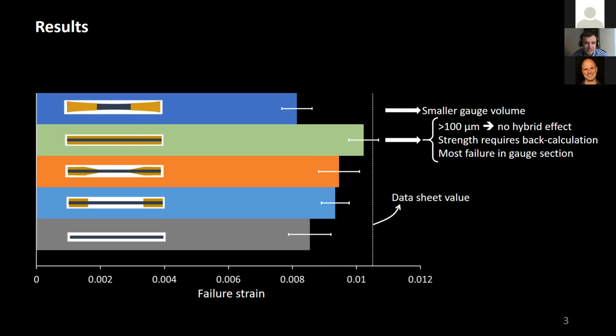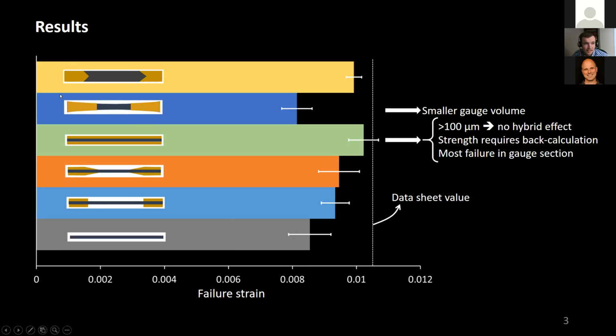the worst test, in the sense that this gave us the lowest failure strain. And I think that is an indication that this was not a very good test, at least not for this specific material. I should also point out that this was the only test that had a smaller gauge volume, which you would actually expect to lead to a slightly larger failure strain or strength. And lastly, we tested the arrow-shaped end taps, and they actually led to pretty good results that are quite well in line with the continuous end taps.